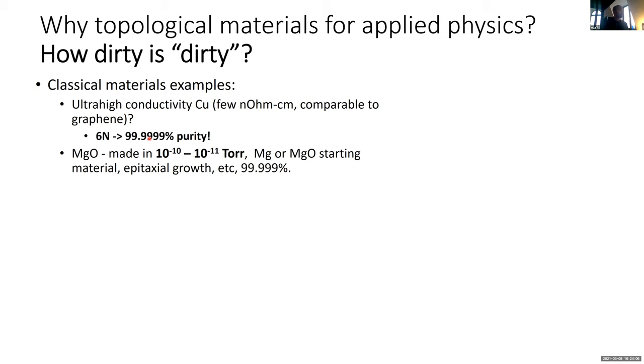Or famously, that MgO, the tunnel barrier in MTJs, magnetic tunnel junctions. Famously, it was Stuart Parkin who was one of the first to realize that MgO was only good as a tunnel barrier, but when it was good, it was exceptionally good, better than anything else, but only when you grew it in very ultra high vacuum. Standard practice of sputtering is to deposit in 10 to the minus eights.